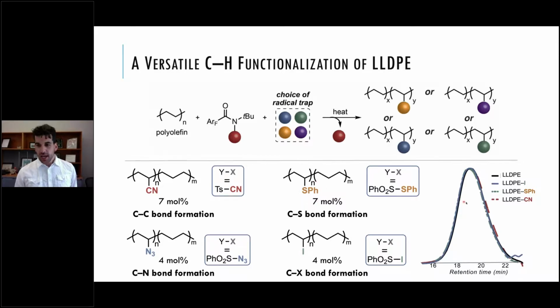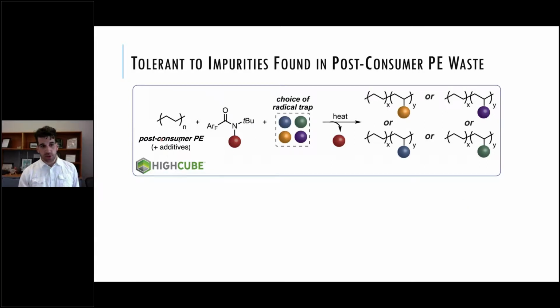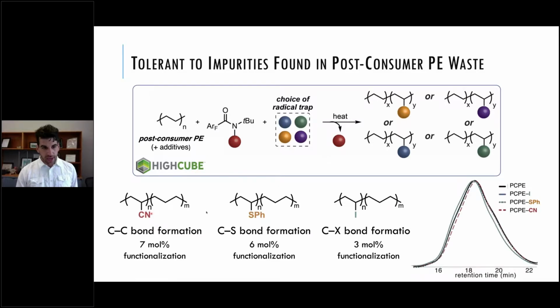And again, this is a size exclusion chromatogram. We don't see at low retention times, or at high retention times, I'm sorry, this peak arising. So this is incredibly selective at adding this polar functionality to the polymer and not degrading the polymer. We even worked with our partners at HighCube Recycling to get post-consumer polyethylene from packaging forms and use that in our reaction. And we're able to see, again, we could add those chemical functional groups in similar efficiency, even using post-consumer polyethylene. And we saw, by different spectroscopic techniques, that there were common additives that are typically found in post-consumer polyethylene. And again, these additives actually didn't interfere with the chemistry that we were developing.